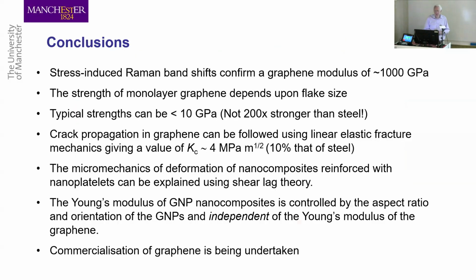Anyway, just to finish off now, hopefully, looking at the mechanical properties of graphene. We've confirmed the modulus of graphene is about 1,000 gigapascals. Strength, however, depends on the size of the flake, more like 10 gigapascals, not 200 times stronger than steel. It's strong, but it's not very tough. Its fracture toughness is quite low.